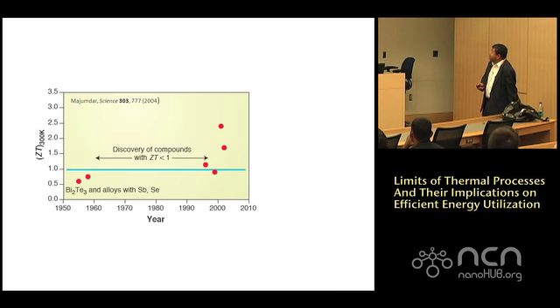So this is the history of ZT at room temperature as a function of year. Bismuth telluride was discovered in 1955, a lot of excitement. Then it went from about 0.6 to about 0.8, and a lot of people got excited. Then for about 50 years, nothing really happened, and people were trying. As I said, this was a Bermuda Triangle, not just for us, but for a lot of other people who got out of it, got into other fields because they just couldn't change this ballgame.